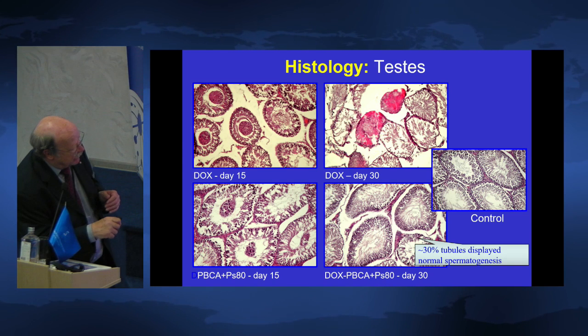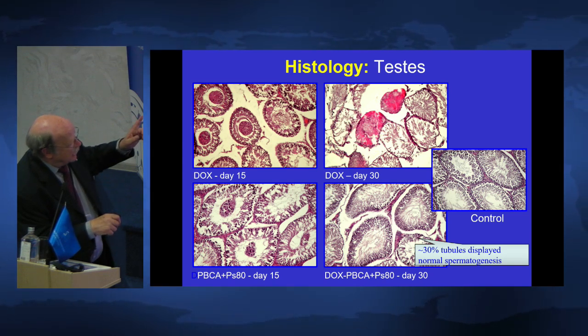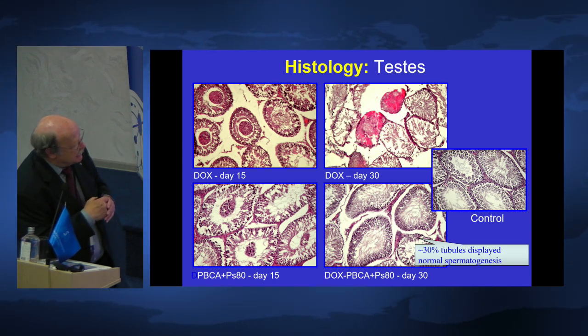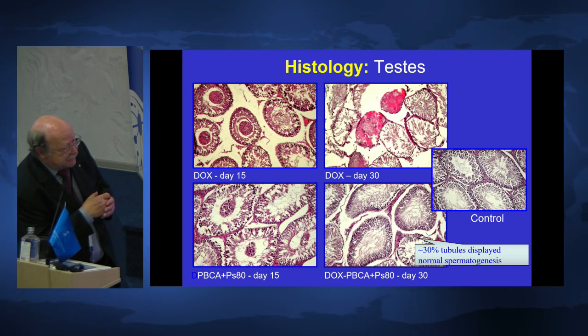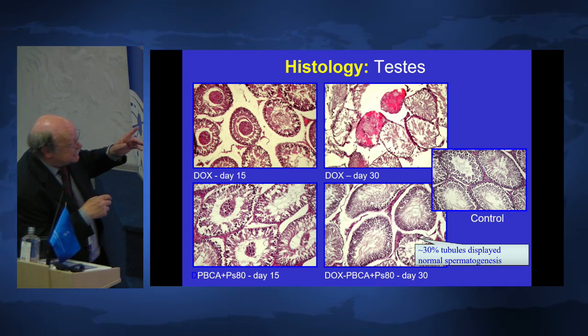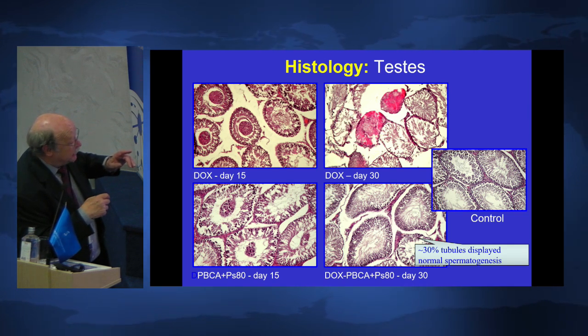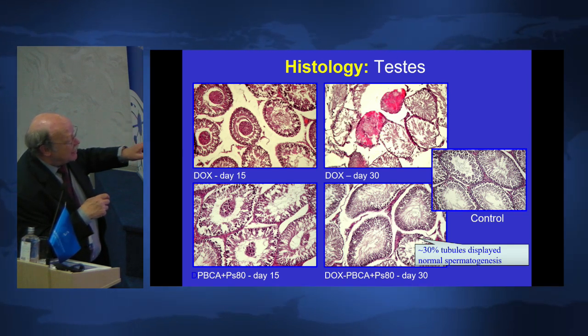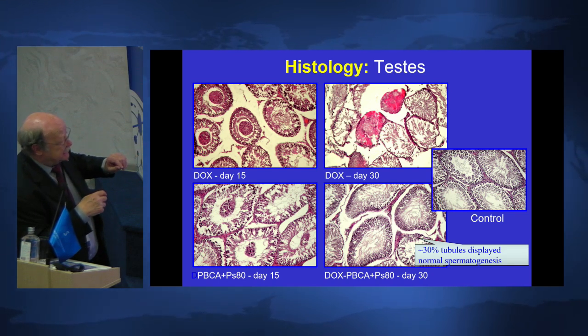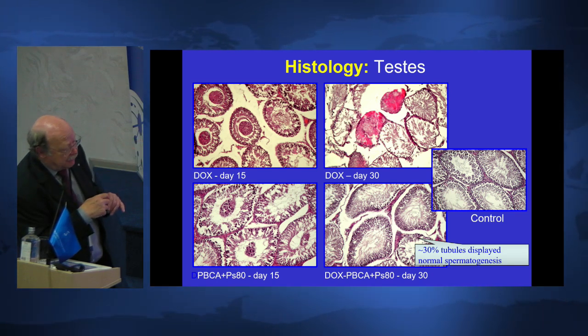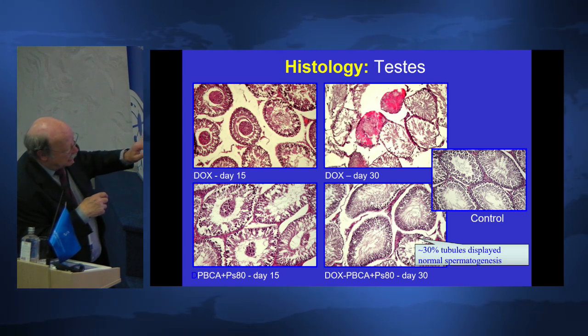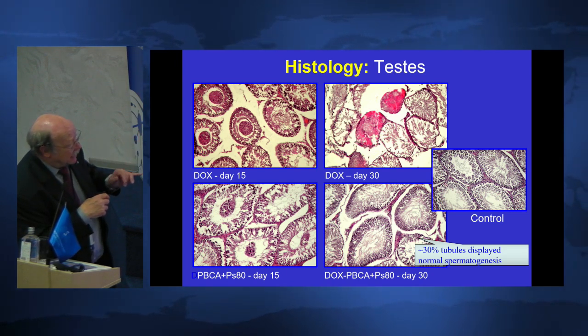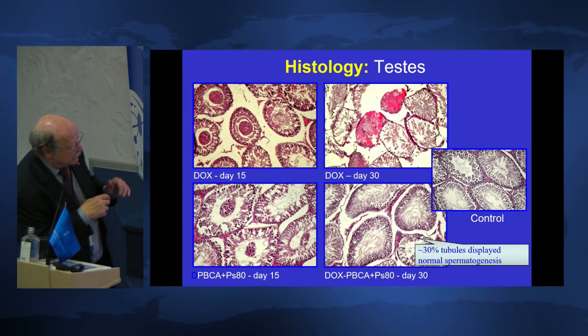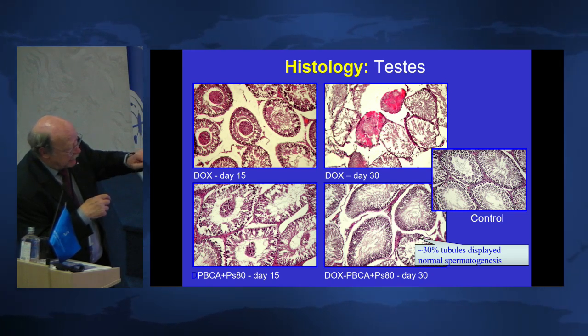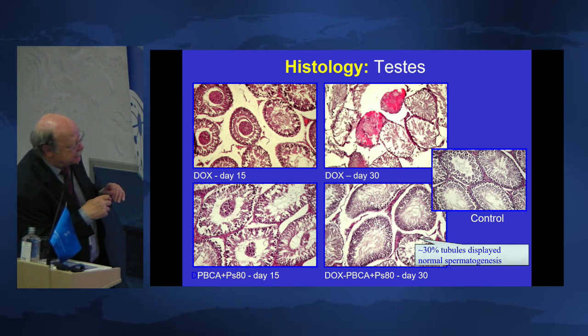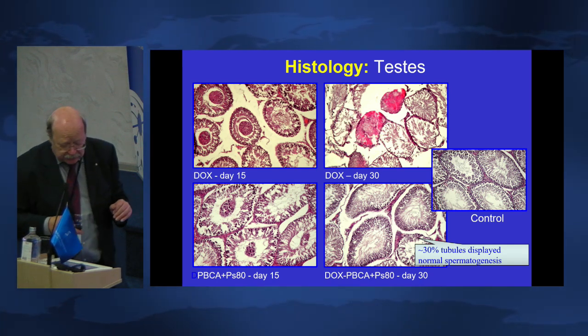Another part of the body where you have severe toxicity by doxorubicin is the testes. Again, on the right side you see the control, and then you see in the upper slides that is doxorubicin by itself. You can see that it is even getting worse on day 30 compared to day 15, and the reverse is taking place when you have these polysorbate-coated nanoparticles. The toxicity is going down from day 15 to day 30, and already on day 30, 30% of the tubules displayed normal spermatogenesis.